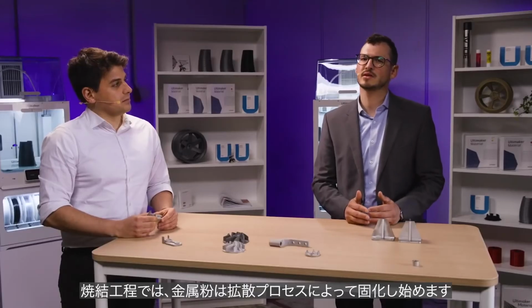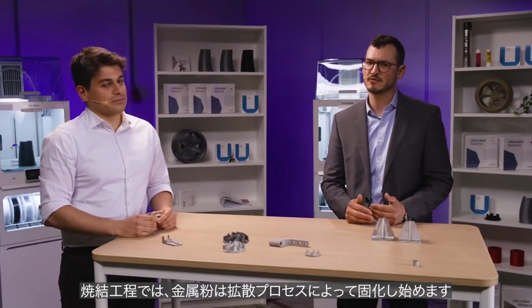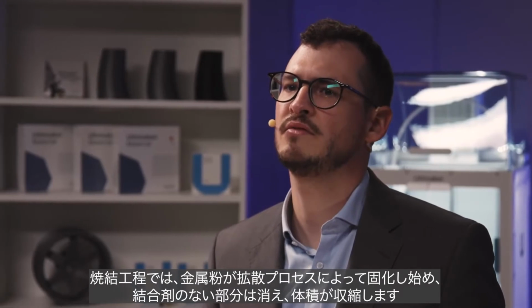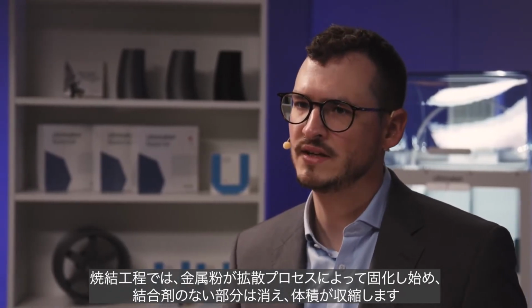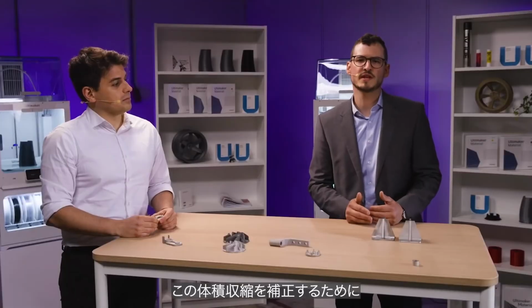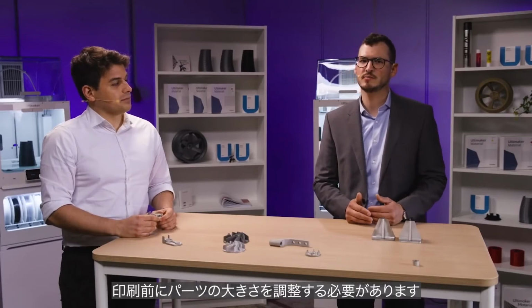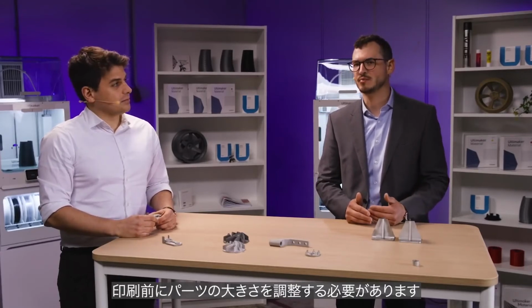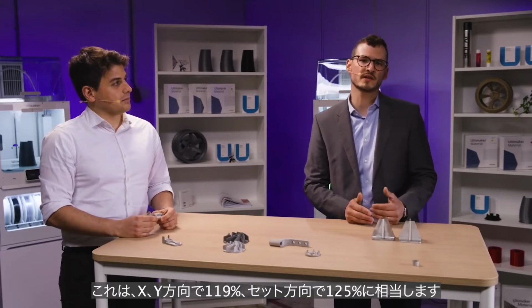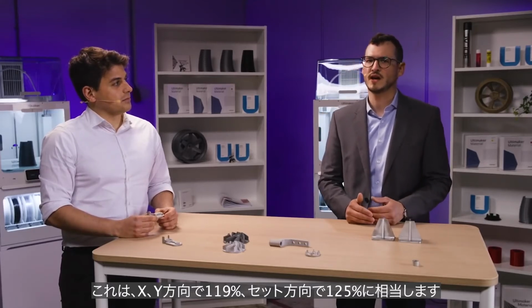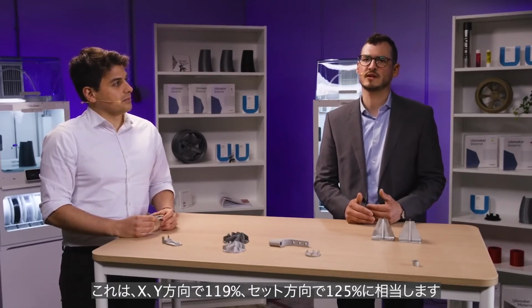During the sintering process, the metal powder starts to solidify by diffusional processes. The empty areas of the former binder vanish and the volume contracts, leading to a shrinkage. To compensate for this volumetric contraction, the parts need to be scaled prior to printing. This corresponds to 119% in X and Y and 125% in the Z direction.